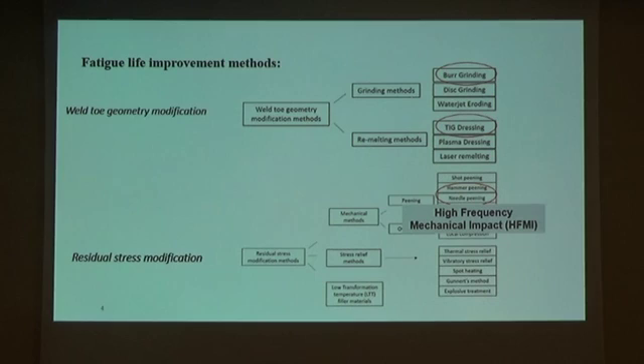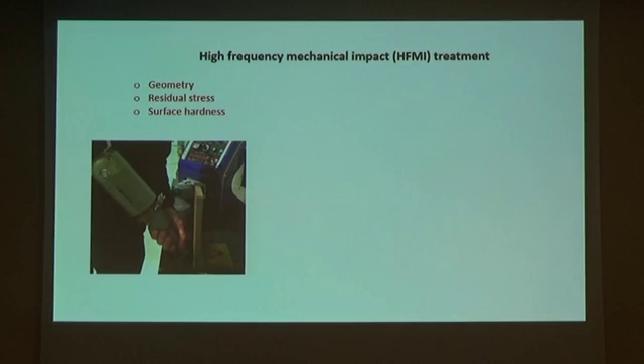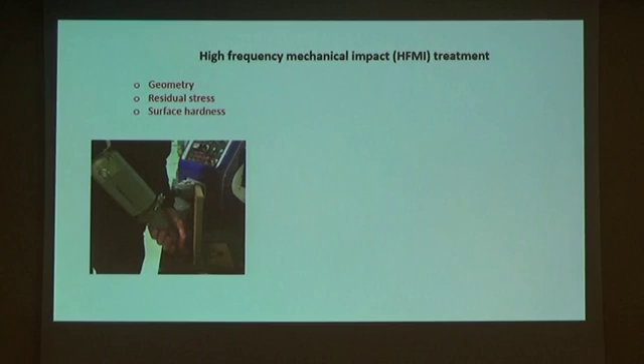The topic of today's discussion is high frequency mechanical impact treatment. What is HFMI? HFMI makes use of cylindrical indenters that are accelerated against the component surface — you can see a picture of that here. They are accelerated against, in this case, the weld toe, using high frequencies. This method increases fatigue life via three main effects.